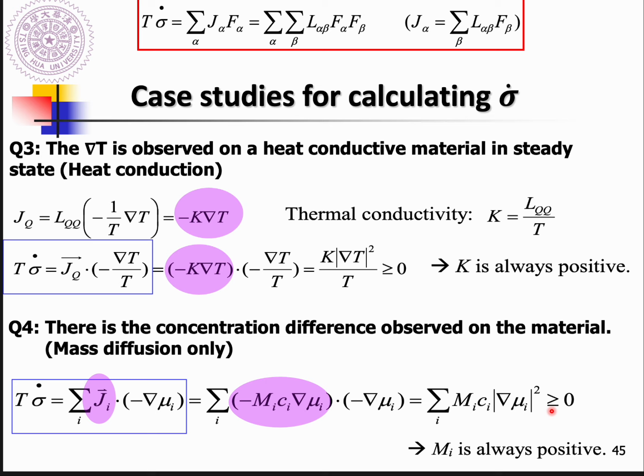So based on this, as long as you know the absolute temperature or average temperature here, the mobility and concentration of these diffusing atoms, and also the chemical potential gradient, then you can easily calculate the entropy production rate per volume. Some students also ask me how to identify the concentration of this diffusing atom. You can use EPMA or SIMS to get the concentration profile of your interesting diffusing atoms. Then you can take the average on this one, so you also can get the C_i.